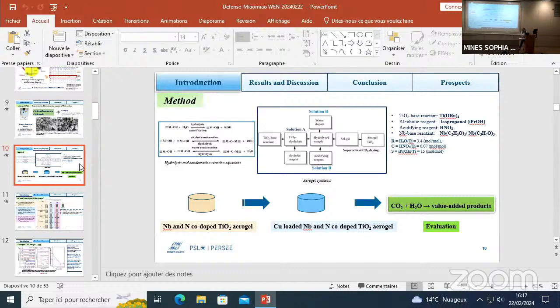What kind of techniques can you use to see if there are still some hydroxide? After every time we change the solvent, we keep the solvent that changed, then do EDX or ICP to see if there is residual titanium or other metal inside, or just the pure acid. But you can simply use some infrared spectroscopy to see if there are some residual alkoxide groups, because you're starting from butoxide for titanium and